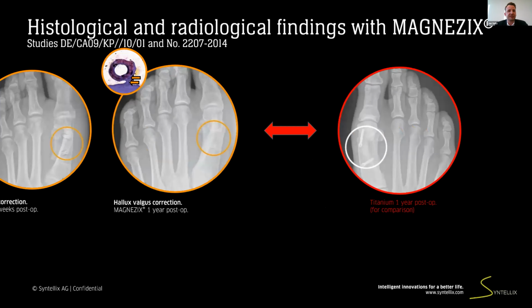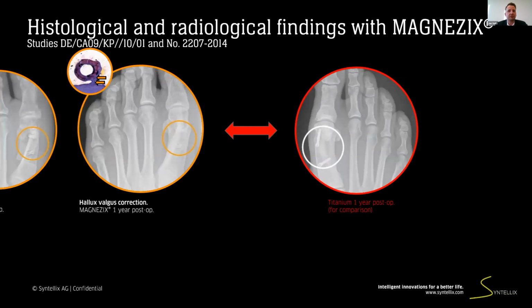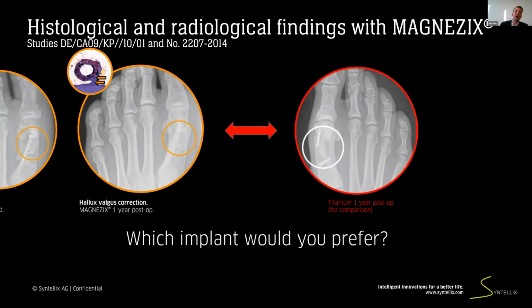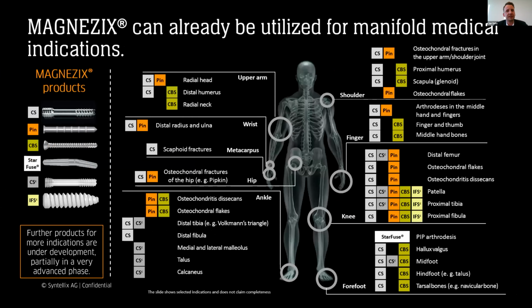Comparing the magnesium-treated situation with a treatment in which non-degradable metal implants were used, the key benefit of this new technology becomes clear. A removal surgery can simply be avoided. I bravely anticipate at this point that most of you would tend to be treated with the biodegradable option if required. Magnesium implants can already be utilized for manifold medical indications. Syntellix's current portfolio covers indications from shoulder to toe.